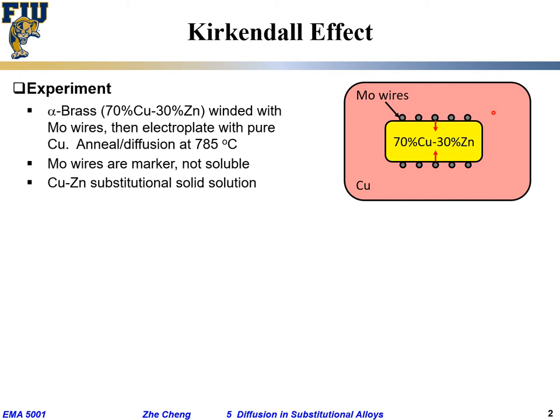Pure copper — if you ever get your hands on high-purity copper fresh from electrolytic bars — actually looks pinkish. The darker color you typically see is oxidized copper; fresh copper is a pink color. They electroplated pure copper onto a piece of brass, but before plating they wrapped the brass with so-called molybdenum wire — moly wire — which they used as a marker.